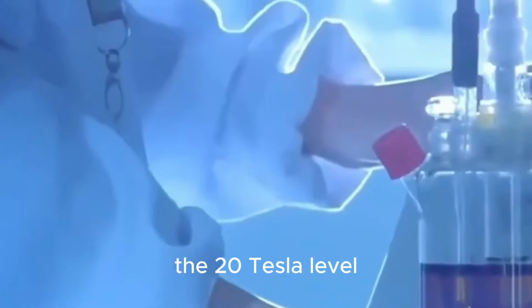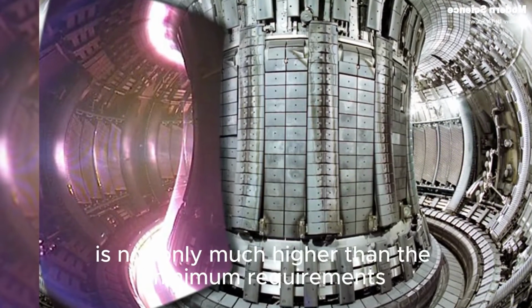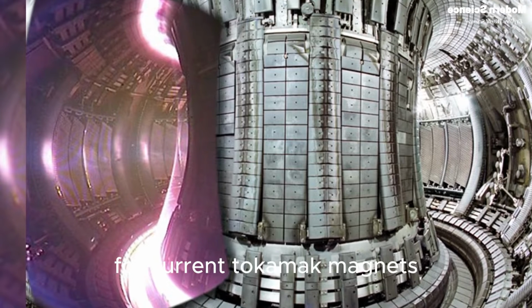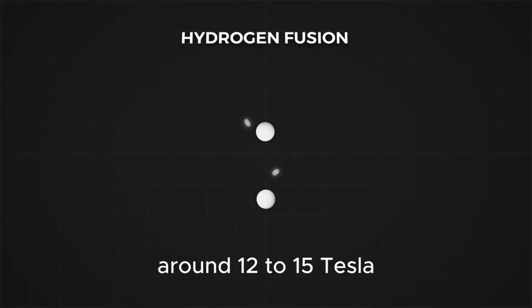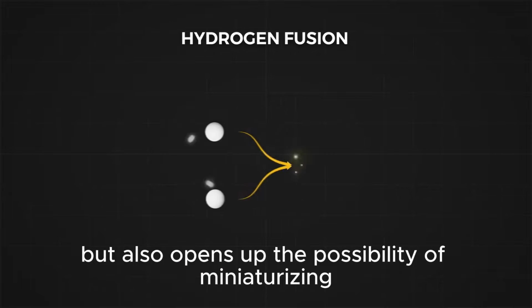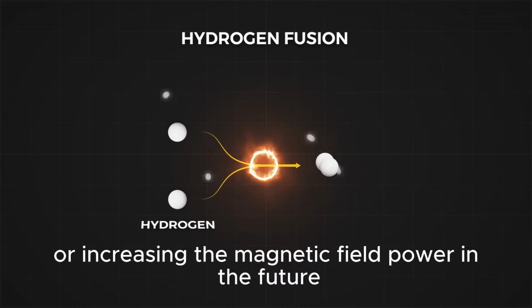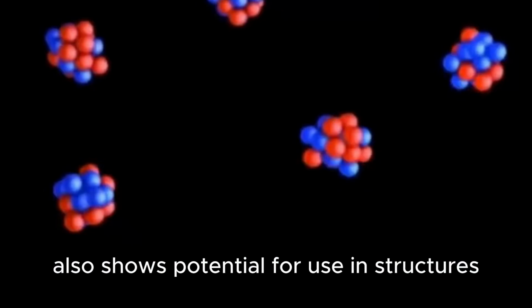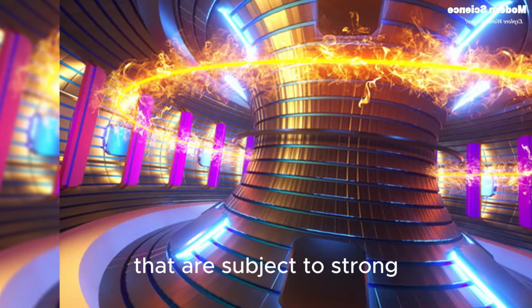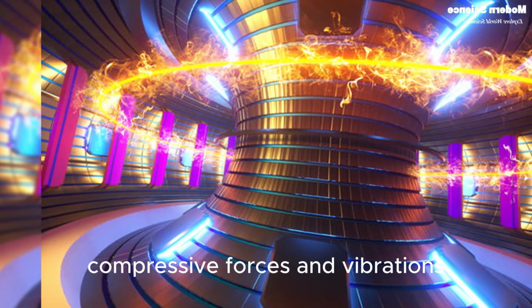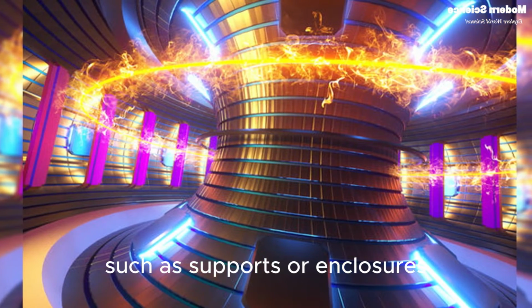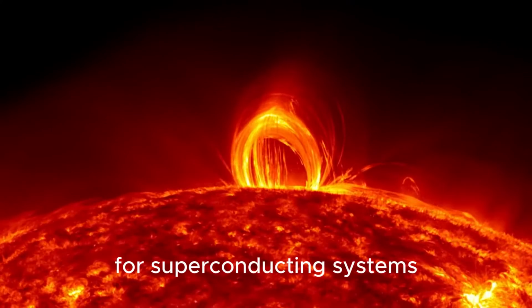The 20 Tesla level is not only much higher than the minimum requirements for current tokamak magnets, around 12 to 15 Tesla, but also opens up the possibility of miniaturizing the device or increasing the magnetic field power in the future. The ability to withstand compressive pressures of up to 1,300 megapascals also shows potential for use in structures that are subject to strong compressive forces and vibrations, such as supports or enclosures for superconducting systems.